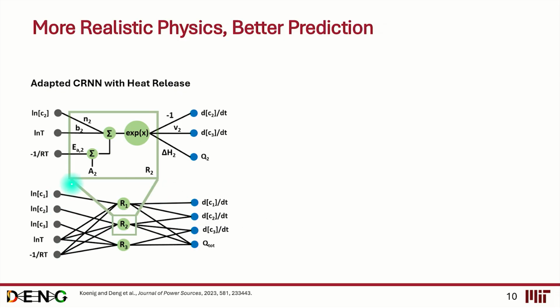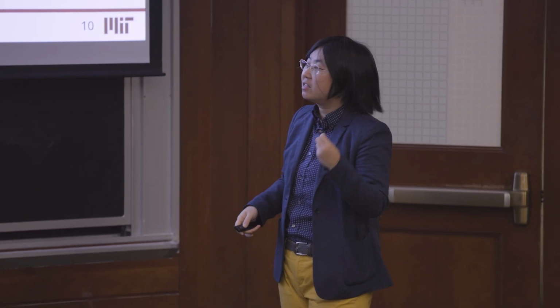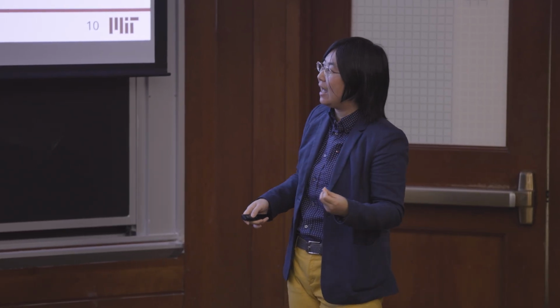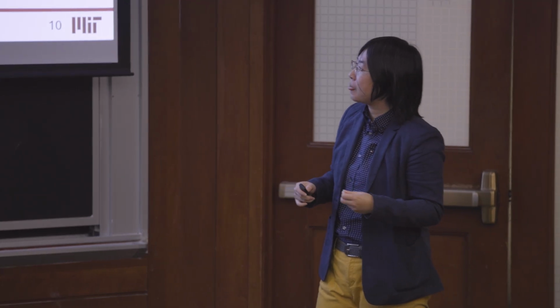For example, we can identify the 3 stages in terms of 3 reactions. The product of the first stage needs to be the reactant for the second stage, and so forth. And for the experiment I just showed you, with the heat flow information, that's a thermal measurement. To incorporate that, we can add another connection describing how the production rate of the materials corresponds to the heat release from the material through this thermodynamic information. And we can model those thermodynamic parameters in addition to the chemical kinetic parameters. As a result, we would be able to come up with a physical model.